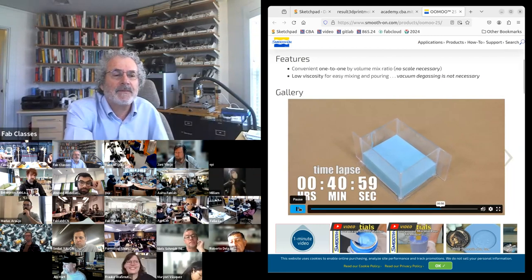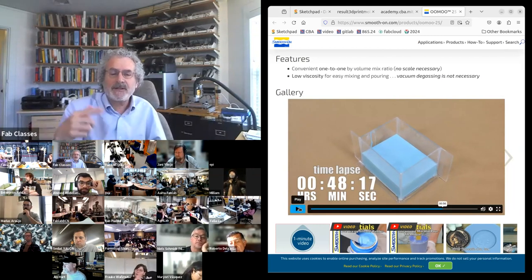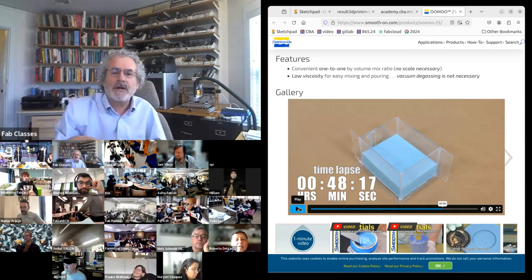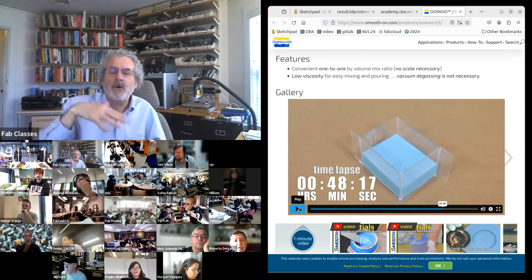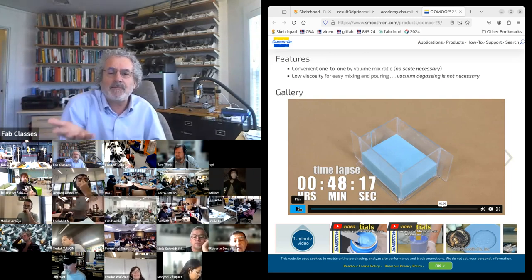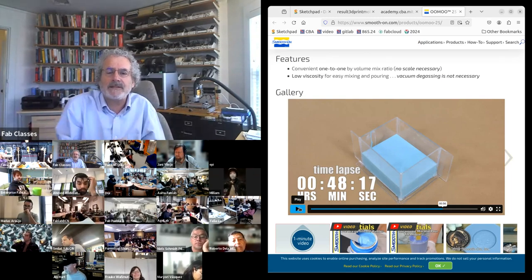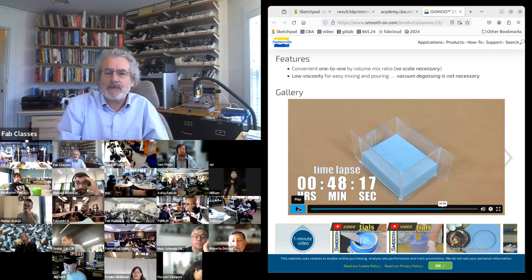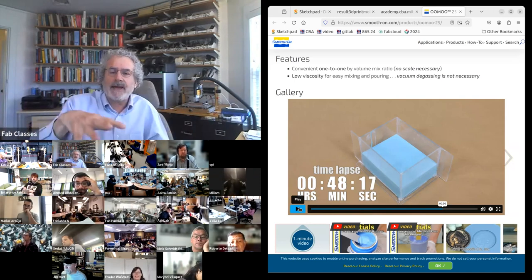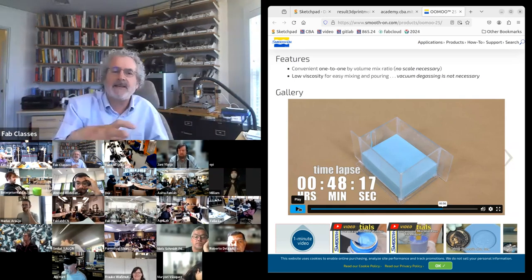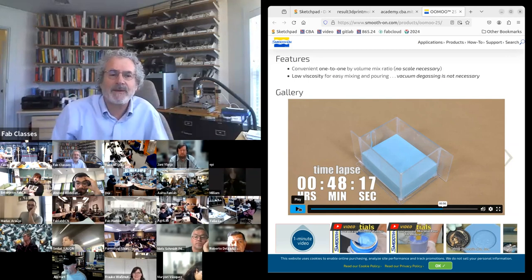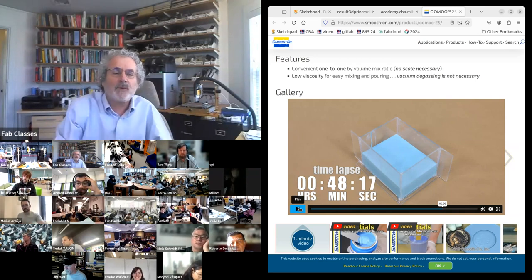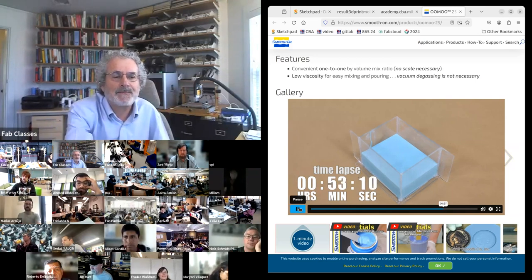Then you let it set. Some of these materials set at room temperature, some need an elevated temperature. The room temperature ones, though, you can demold much more quickly if you raise the temperature. This is similar to bread rising. So you can wait overnight for a silicone at room temperature. If you use a thermal lamp on it, like a desk light that's incandescent, which is increasingly less common, or put it in a low temp toaster oven, within an hour you can demold it.